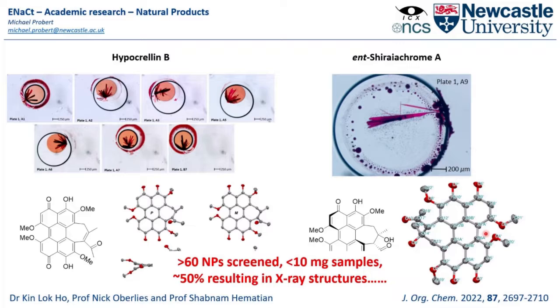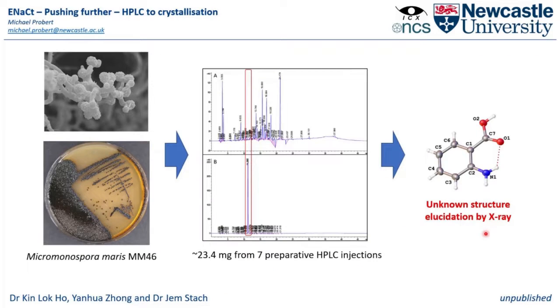If we want to take this further, our ideal situation is to push this technology a little bit harder, and one of those options was to try and go directly from HPLC into crystallization. And this was a project in collaboration with Jem Stach, where analysis of a compound gave fragments that had the wrong mass for anything that was expected to be in the system. And so from a small amount of material, we analyzed the material and resolved the structure. It had nothing to do with what they were expecting, but gave full resolution and was an unknown structure as well. So it shows that the potential for this is there to go almost direct from HPLC to crystallization work to full crystal structure analysis.